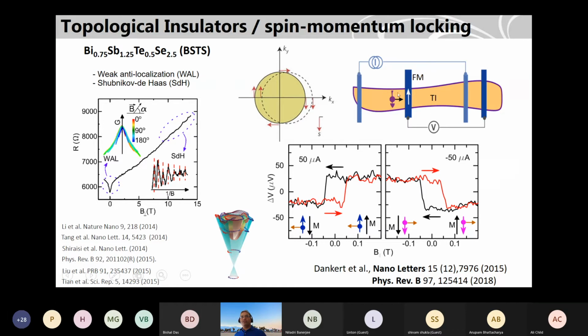So we apply current, and we are measuring with the ferromagnet what is happening here below the contact by this voltage probe. So what we do, we apply the in-plane magnetic field to switch the magnetization of this ferromagnet, and the spin direction in the TI we decide by applying the current. So when the current is in this direction, spin is like that. When the current is in the other direction, spin will be opposite because it's spin momentum locked. So that's what we see here.